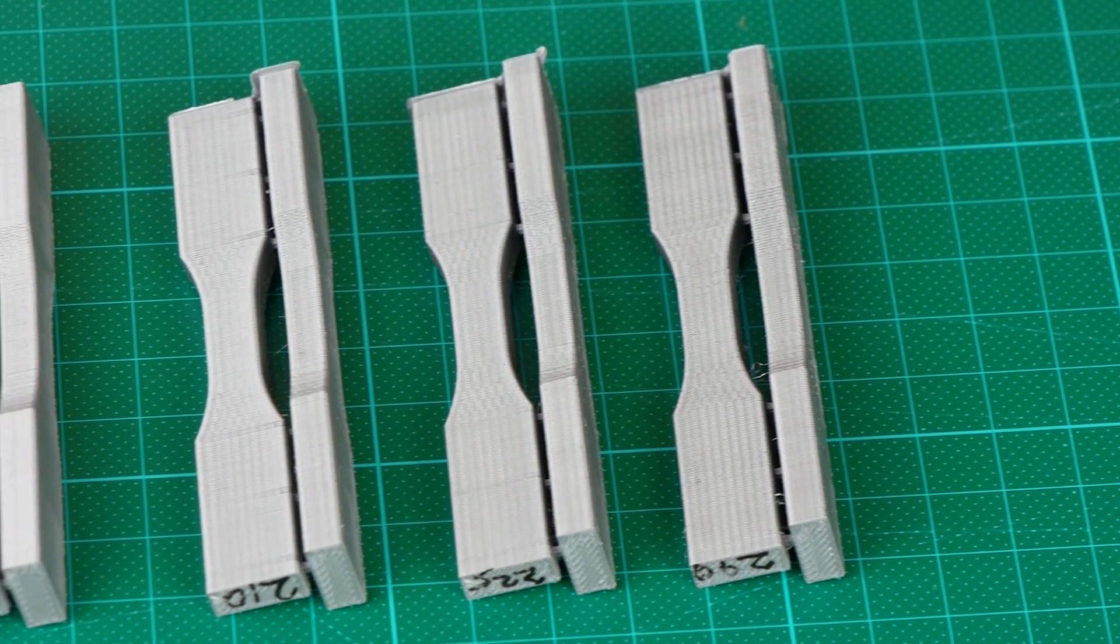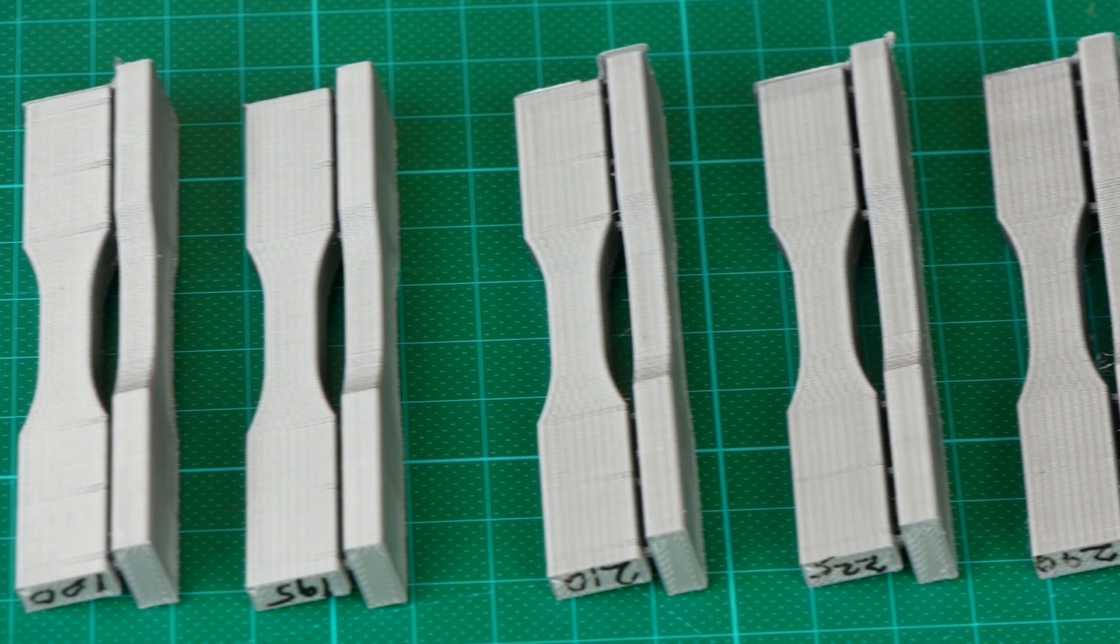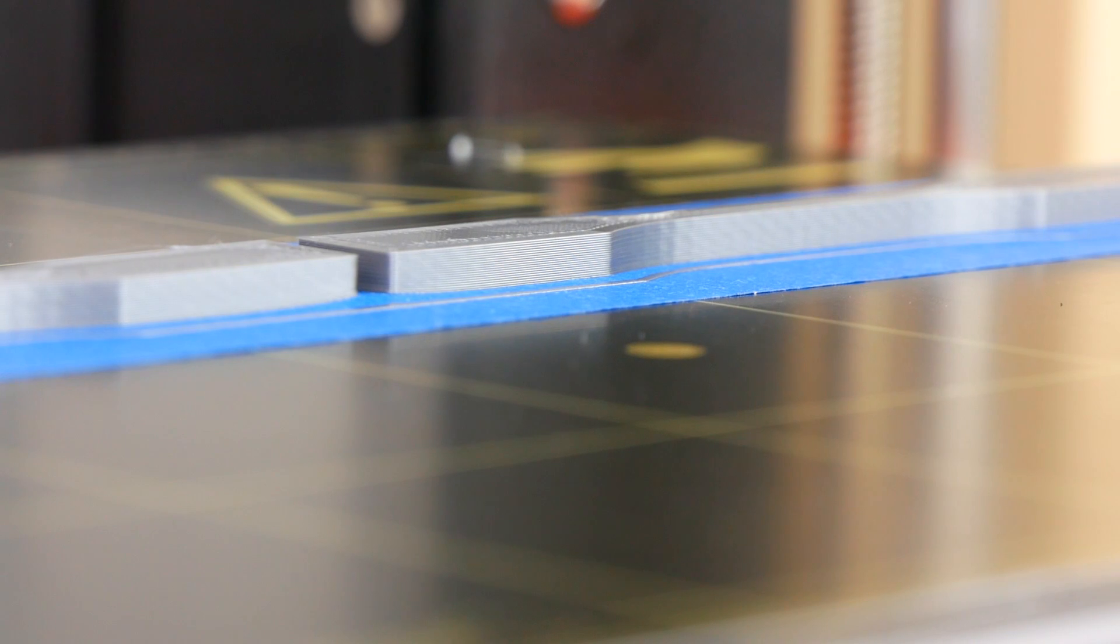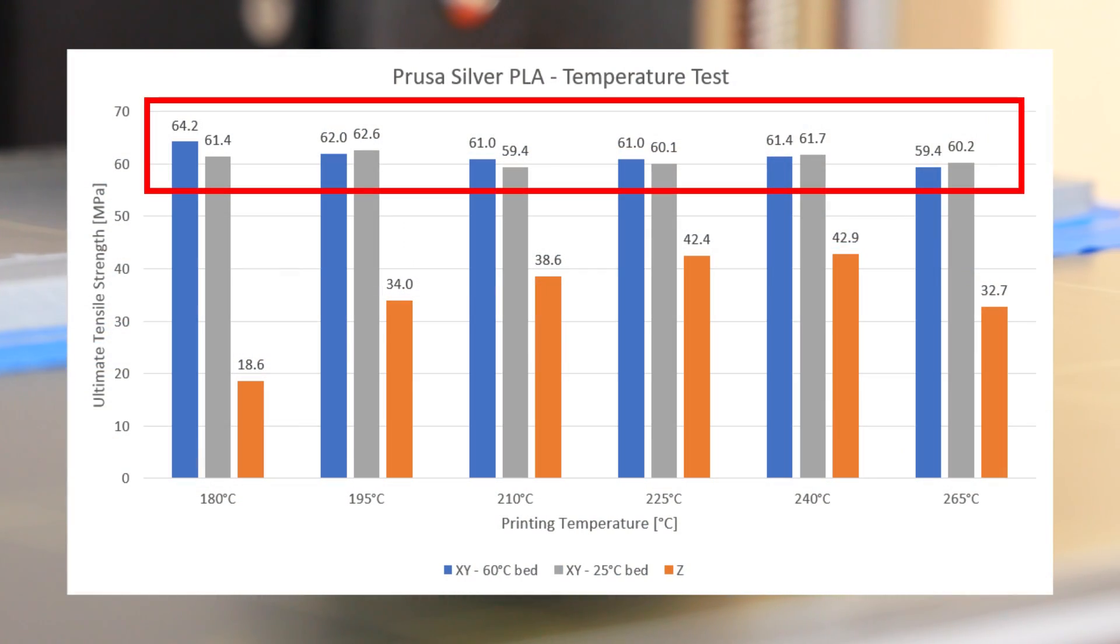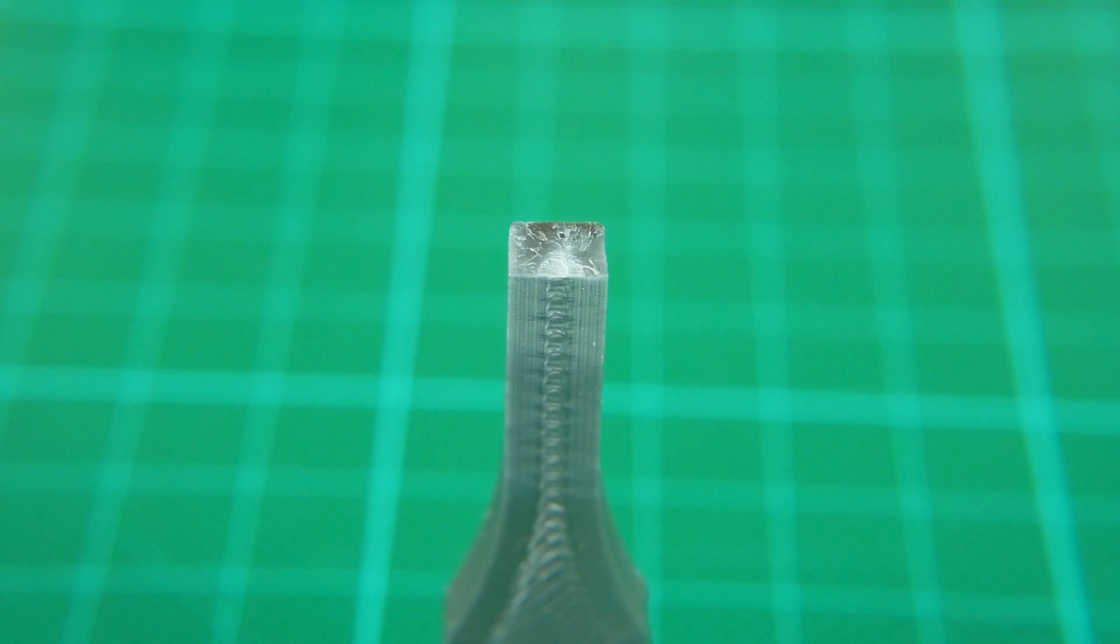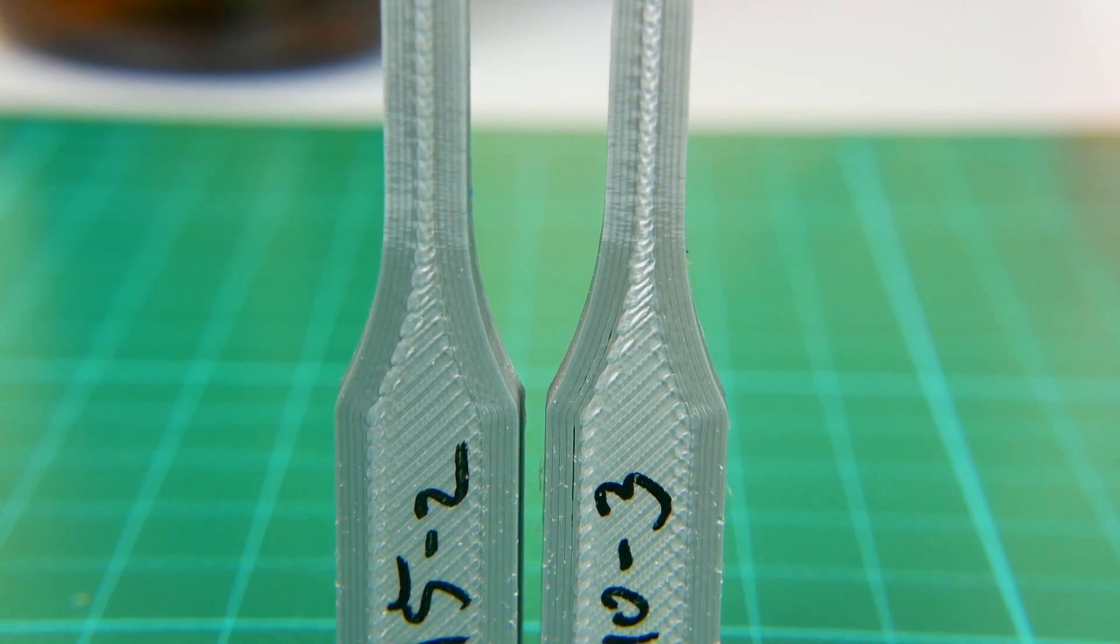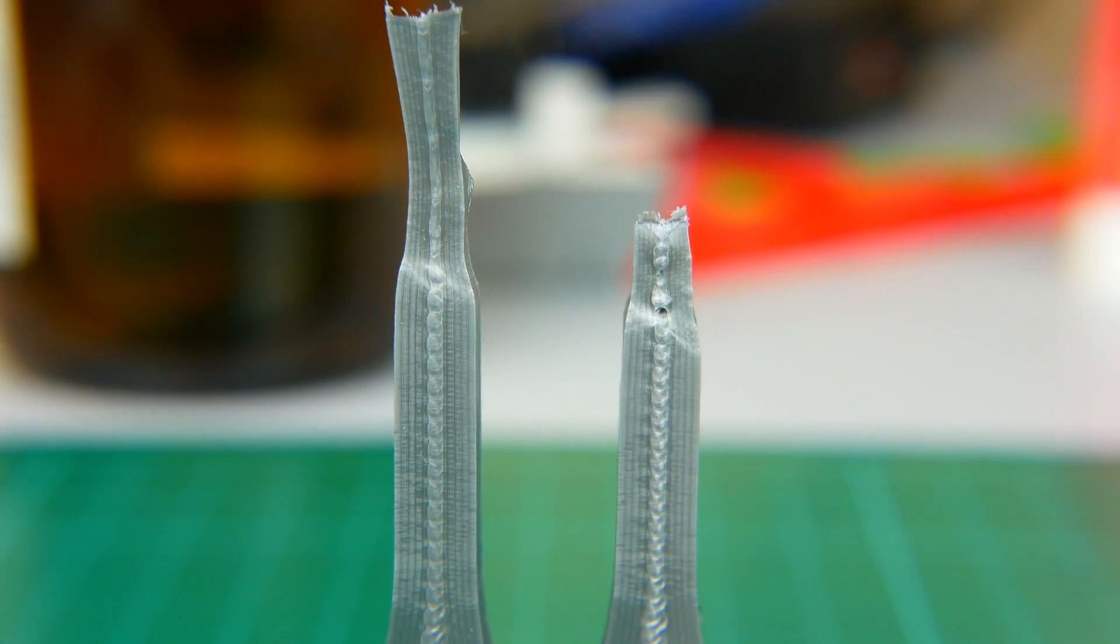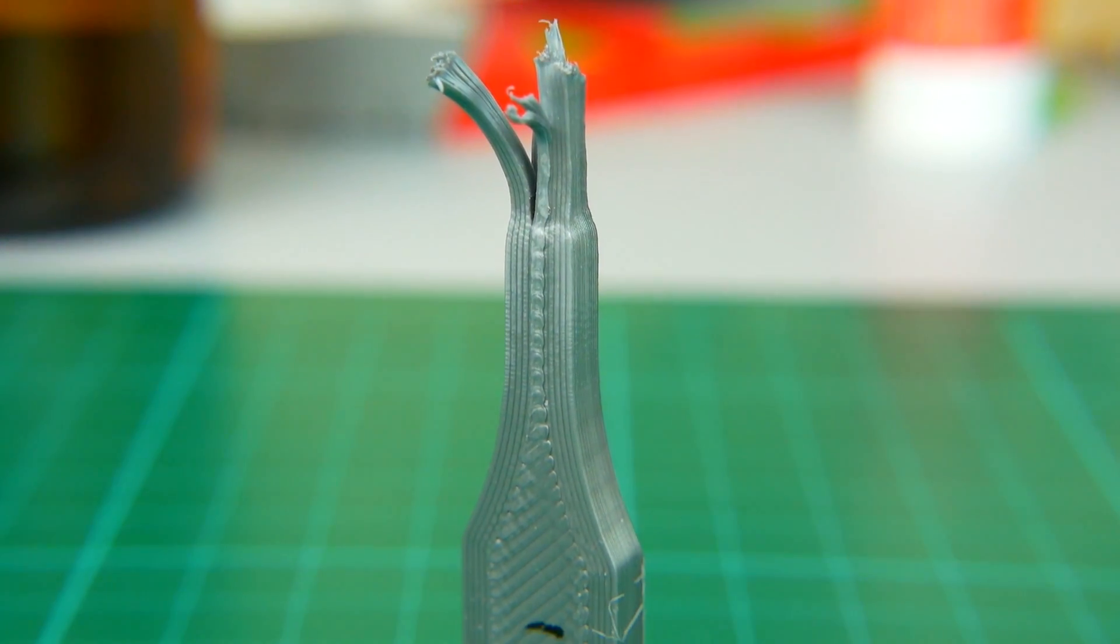The upright specimens should not be affected by this problem since the areas under test are decently far away from the heat bed. So I reprinted the lying specimens without the heater on, which is actually not too easy. The ultimate tensile strength of these were not too different from the other ones. The only thing which really changed was the failure mode. The ones printed on the 60 degree bed failed brittle, whereas the ones printed on the cold bed strained a neck before they broke, which makes them more robust. This doesn't change my conclusion but shows me that I need to investigate heat treating PLA soon in more detail.